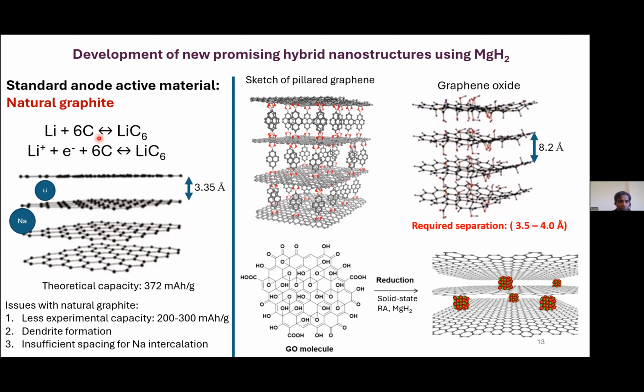For understanding this, I want to take your attention to this graphitic structure. It's a pictorial representation. When you use graphite as anode active material for a lithium-ion battery, what actually happens is lithium intercalates in between the layers. And the interplanar spacing required for the intercalation of lithium is 3.35 angstrom as far as the graphitic structure is concerned, and that is there. The distance is sufficient. But the same thing is not true for sodium. It is a heavier, bulky atom and ion as compared to lithium.